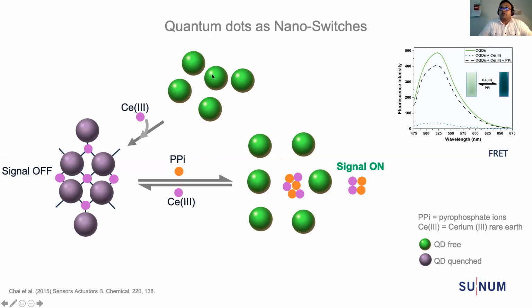This is one of the best examples where we can use nanocrystals. If you have a colloidal form of nanocrystal, this is one typical example that I found suitable to show you here. These are carbon dots, quantum dots made of carbon. In the presence of cerium-3, these carbon dots aggregate and form a cluster that can be seen visibly. And the photoluminescence property changes. The emission property of these quantum dots changes as they form a coordination complex like this, which essentially quenches the fluorescent emission of the quantum dots, which we call the signal off.